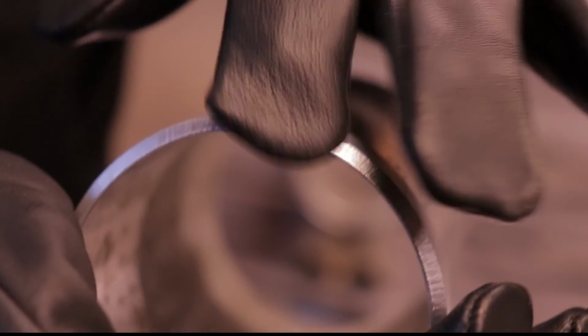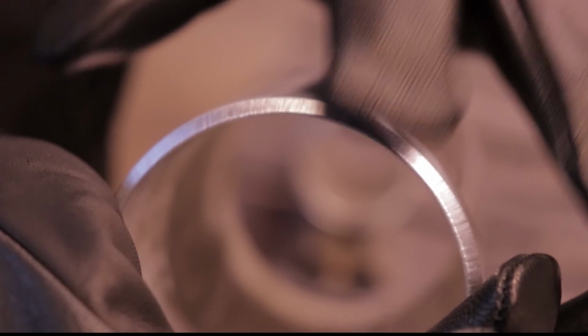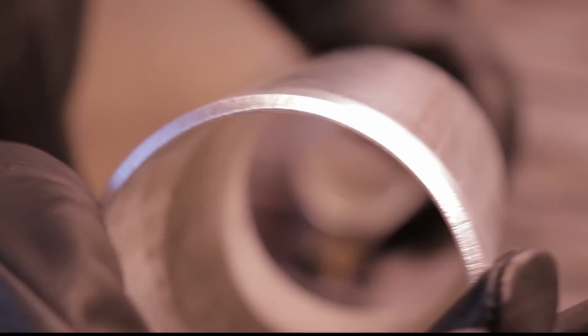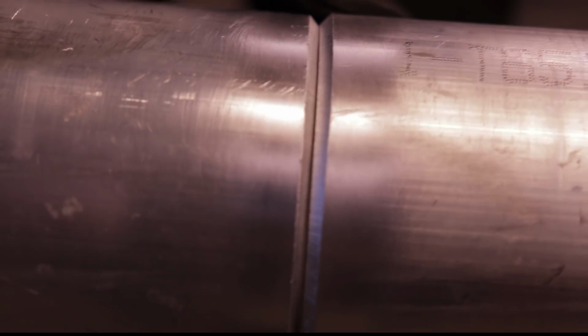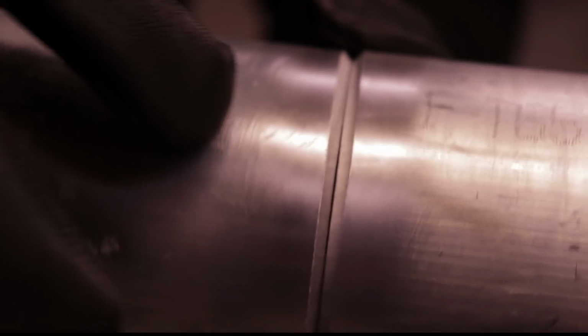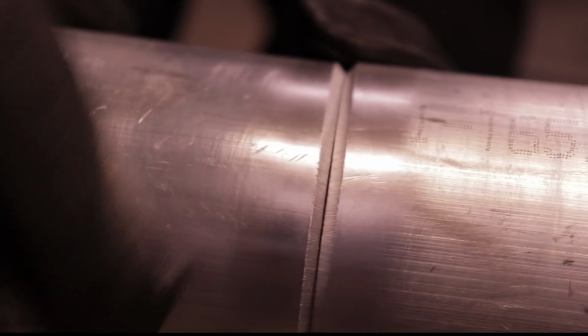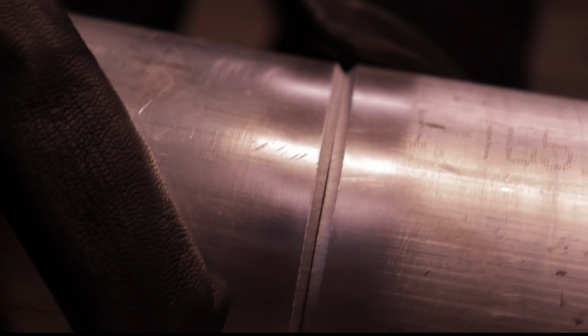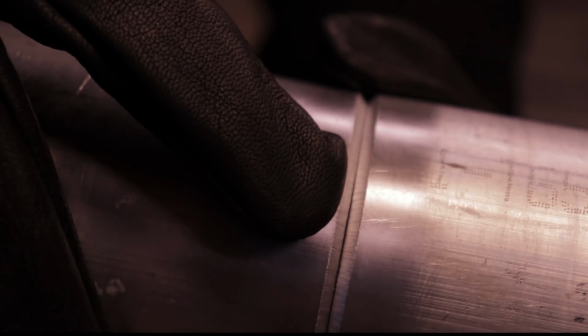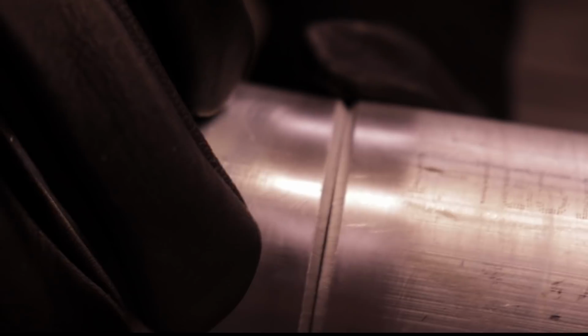If I'm doing 2-inch Schedule 40, I usually still 45-degree bevel those, and that gives it enough to still get in there. And when I put them together, there's no gap, it's flush. When you 45-degree bevel them like this, it takes a little more heat than if you had a J groove on there. But when it's thin like this, you can still get away with it.